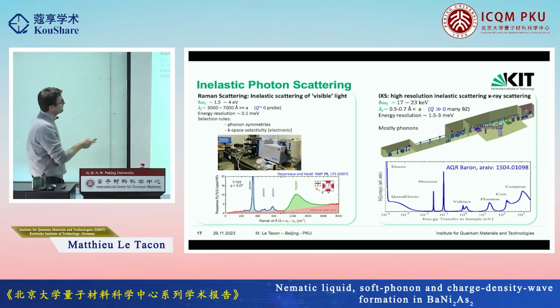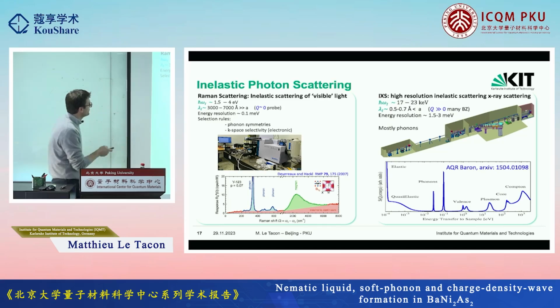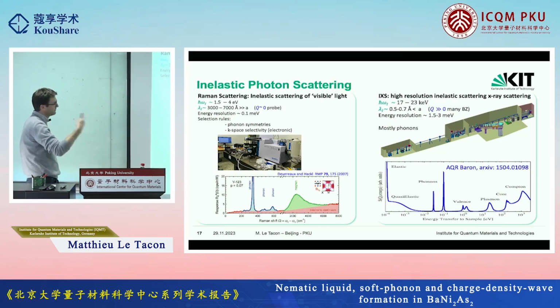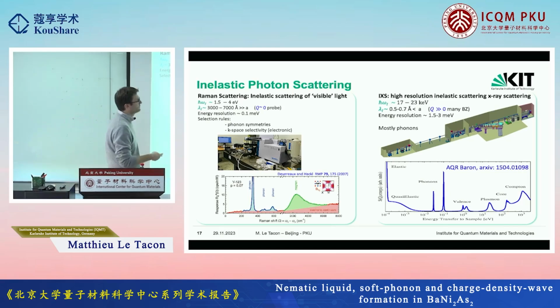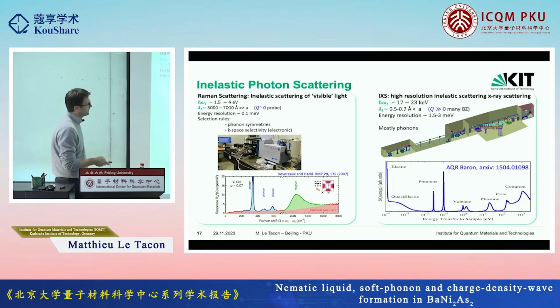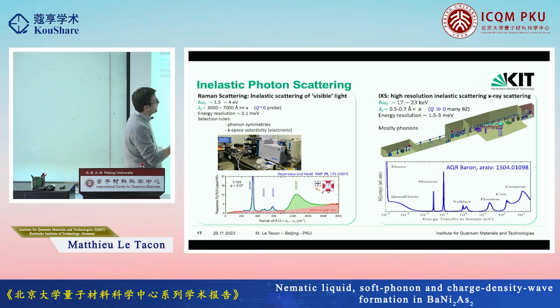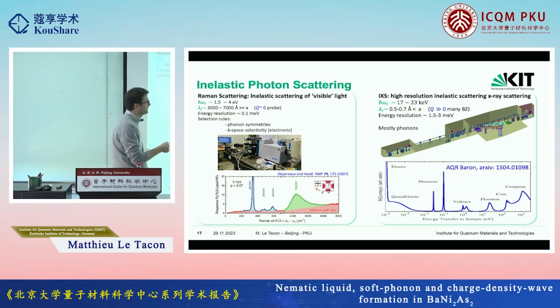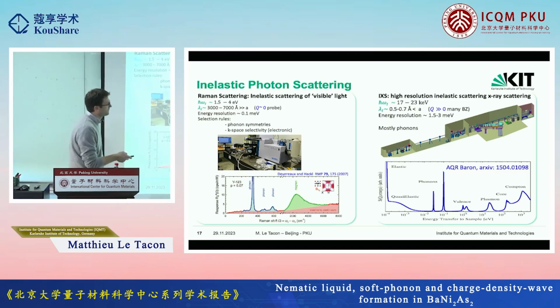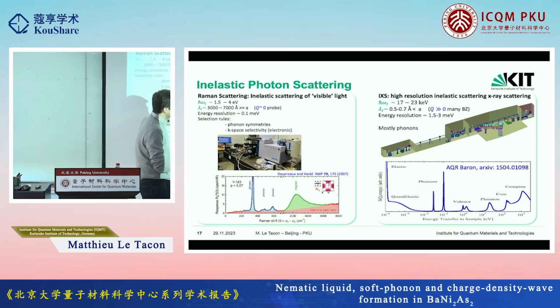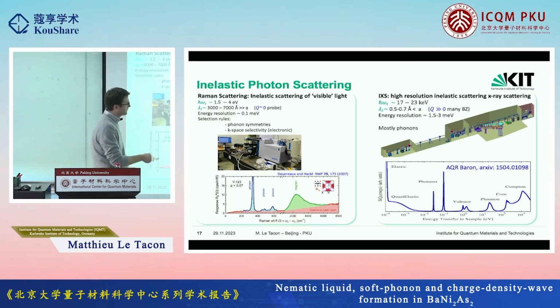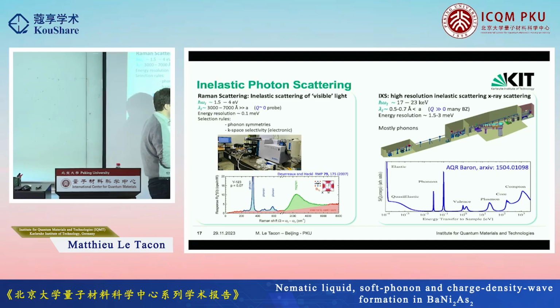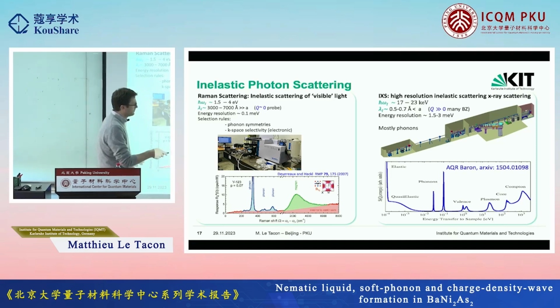Now, if you want to go away from Q equals 0, you have to use a photon which has a shorter wavelength, so carries a higher momentum and allows you to transfer some momentum to the system which is reasonable compared to the size of the Brillouin zone. And this we do using inelastic X-ray scattering. So we go to the synchrotron beamline and scatter inelastically photons in the tens of kilo electron volt range, with an energy resolution of 1 to 3 millielectron volt. There again, there are many kinds of excitations you can look at. Elastic scattering is a zero energy loss channel, so it's a kind of diffraction experiment, but with energy resolution, if you like. But we're mostly going to focus here on the phonons in the second part of the talk.